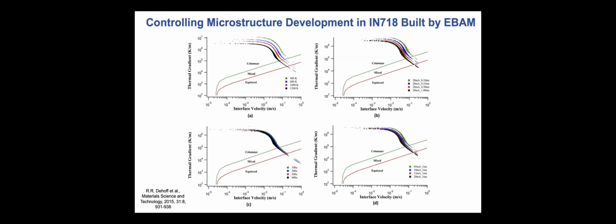And then what we have here in these colorful sweeps are the GV conditions, so the thermal gradients and the solid-liquid interface velocities that are actually experienced in the melt pool. Those GV combinations are really important with respect to the location of these columnar to equiaxed transition curves, because that will dictate our microstructure development, even in additive manufacturing. So these are for different processing scenarios that impact our GV traces in the melt pools that we experience in additive.